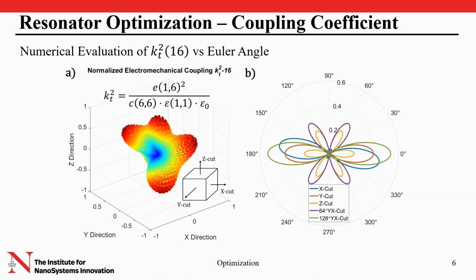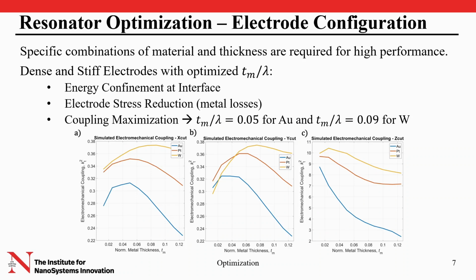Moving forward, the first step is, of course, to optimize the coupling coefficient. Lithium niobate is anisotropic, therefore its properties depend on the Euler angle orientation. And here we can see the numerically evaluated coupling coefficient as a function of the Euler angles of rotation, as well as on the right, a focus on commercially available cuts. Additionally, the coupling coefficient also depends on the electrode configuration. In particular, only specific combinations of material and thicknesses are necessary to achieve high performances.